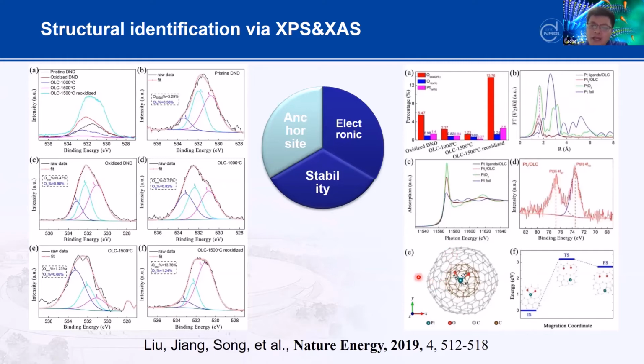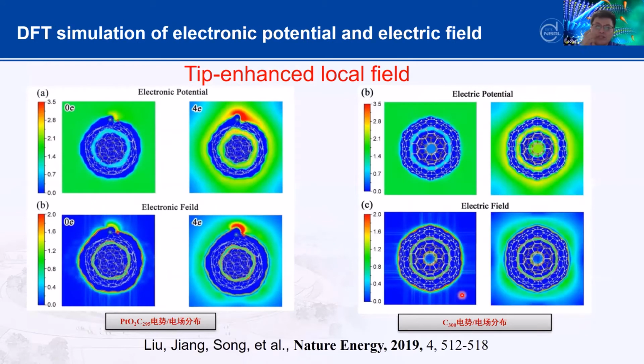And we really simulate the thermal stability. We found if you directly put the Pt on the carbon onion, it's not thermally stable. If you put two oxygen as the arms to catch this Pt, they're really stable. Meanwhile, we do this very important simulation. We found if you simulate the carbon onion without any Pt on the surface and apply an electric potential, you do not see any local field. But interestingly, if you put the Pt on the top and on the surface, when you apply the potential or the electric field, you will see some local electric field. This is really called the tip-enhanced local field.